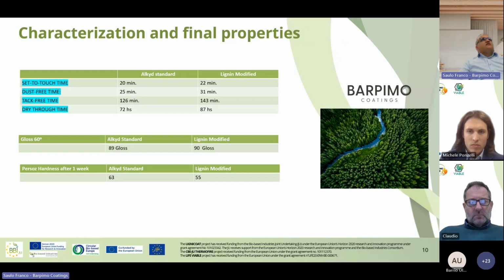After that, we started characterization: set-to-touch time, dust-free time, tack-free time, and dry-through time. As you can see, we have a little bit of difference between alkyd standard and lignin modified, but it's something that is assumed. It's not bad. Gloss is also very similar, and the hardness a little bit less, but it's also assumed for our application.